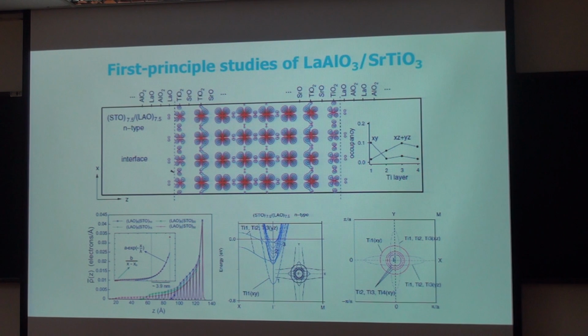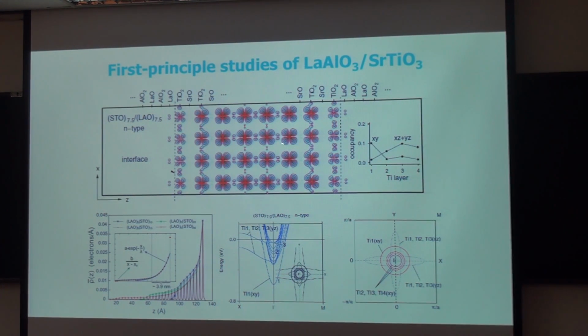For our theoretical first principle studies, what can we do? For this system, using the first principle density functional approach, we can study the charge distribution at the interface. We can find from this plot that the two-dimensional electron gas has a region of several nanometers. We can also study the orbital occupation of this two-dimensional electron system, where we can find at the interface it is mainly from the dxy orbital. At the inner part, there's xz and yz orbital occupancy. And we can also study the Fermi surface of this system and tell some important information on the transport as